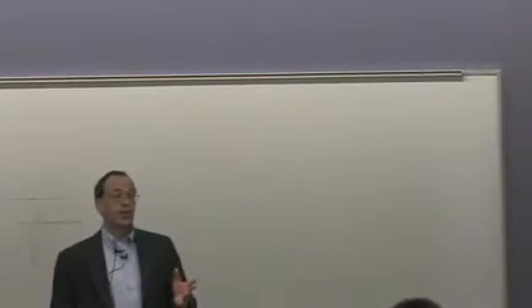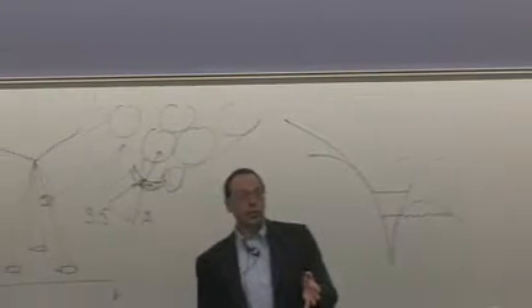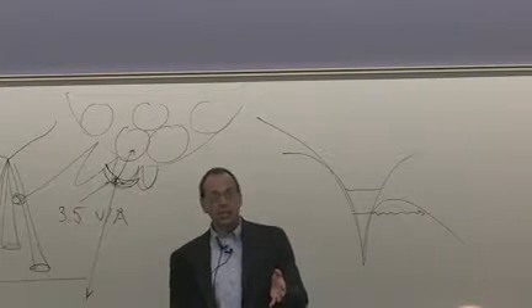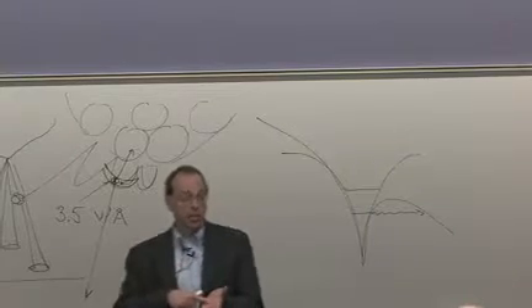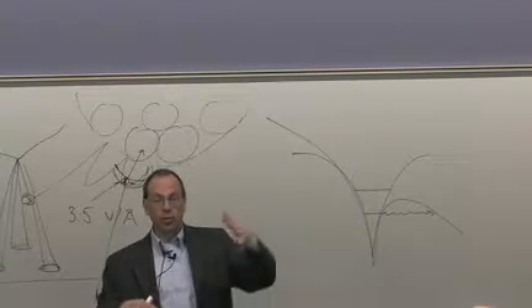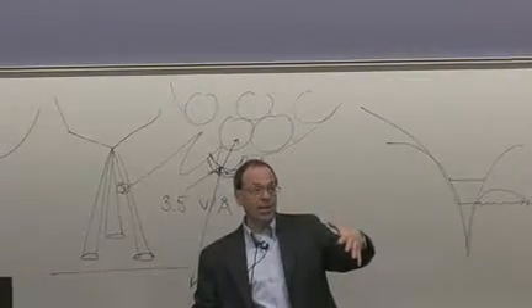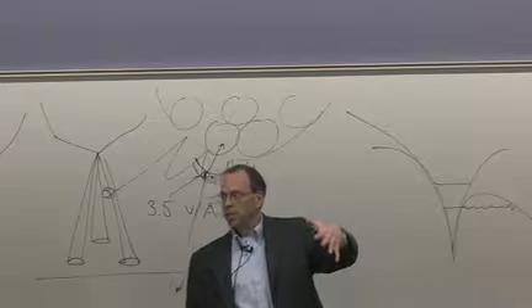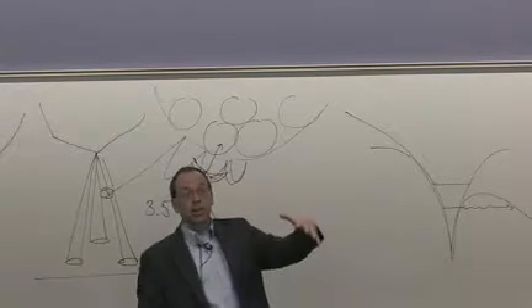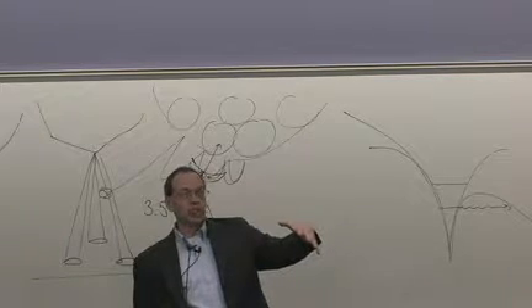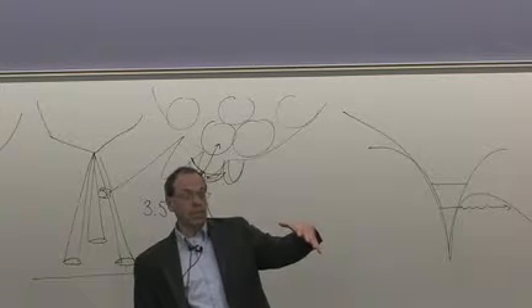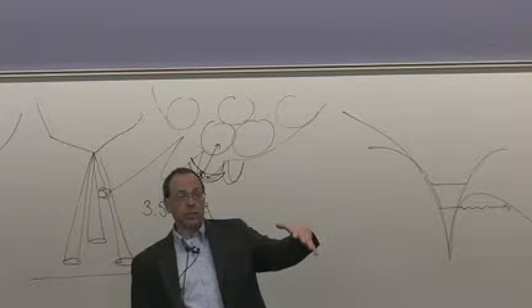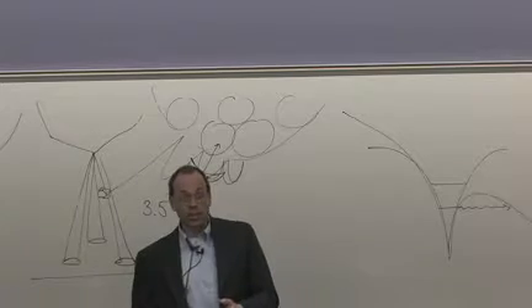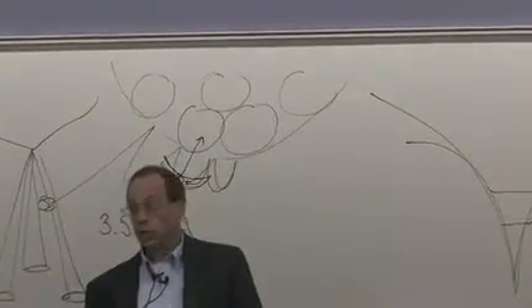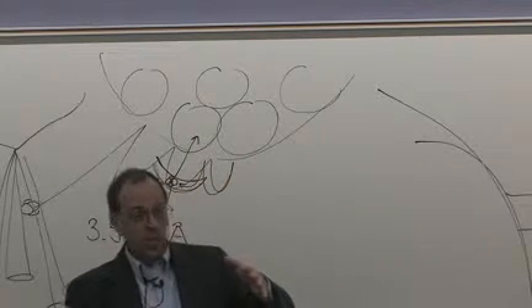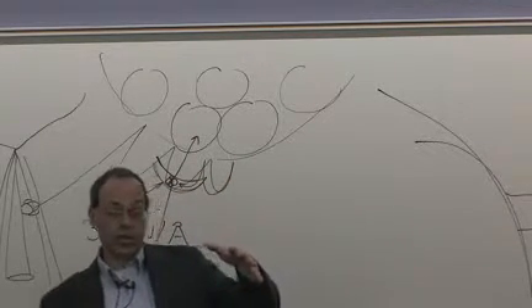Yeah, actually, it's very interesting. You may be familiar with the electron beam version, called EBSD, where you have an electron beam come in and hit a crystal. It has a very interesting diffraction pattern, and you look at a phosphor screen nearby, and a computer system recognizes the pattern. I think Bruker and Oxford make these kinds of instruments. A computer says, oh, I can tell you exactly the orientation of that grain. Now, in principle, the same could happen with an ion beam, but there are technical challenges. The physics may be a little different because it's less of a wavelength phenomenon and more of a blocking phenomenon. But still, in principle, there's a blocking pattern you could see. A helium beam comes in, hits a grain, and the pattern will tell you the orientation of that grain.